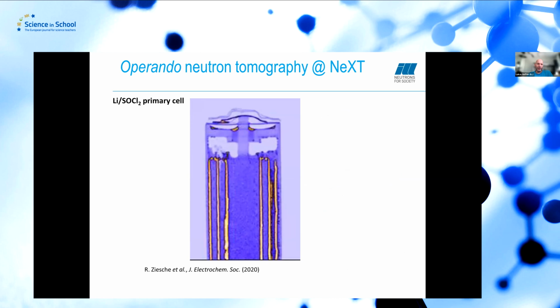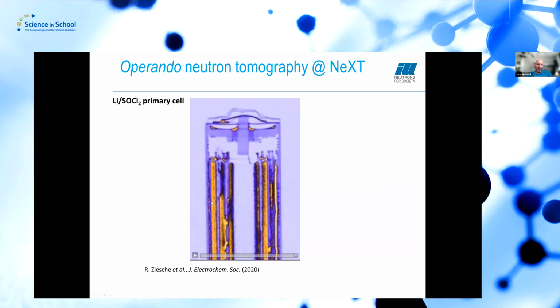So, operando discharge of a primary cell, here a thionyl chloride cell. It has a liquid electrolyte, which is in a porous carbon structure for the electrical conductivity. And we have a pure metal anode, a lithium metal anode, which is connected to the outer casing here and provides the negative electrode. And the carbon structure is connected to the positive electrode here. So what happens when we discharge the battery? We see that the electrolyte, the liquid electrolyte, and also the cathode itself gets consumed. So there's SO2 gas and sulfur being produced, and we see that the lithium goes away from the lithium metal anode to these compounds that are forming here in the former cathode material.